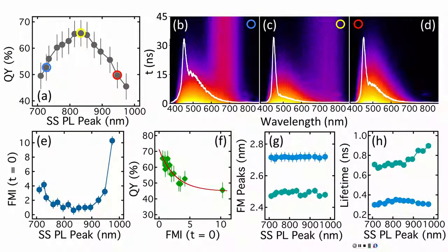These are all below the Bohr radius. 2 to 4 nanometers is the size of your crystals? Yes, the diameter, not the radius. And do you know the size of the Bohr radius for this system? It's about 4 or 5 nanometers. Okay, so you are still in a very strong confinement regime, right? Strong confinement regime, yep.